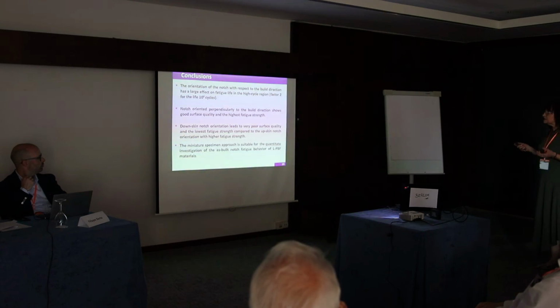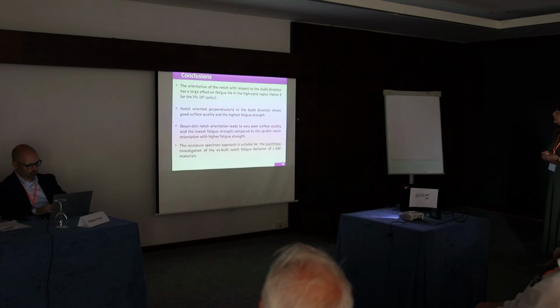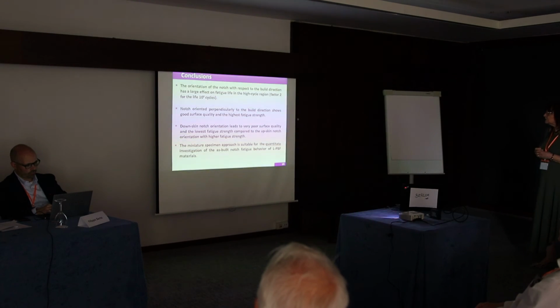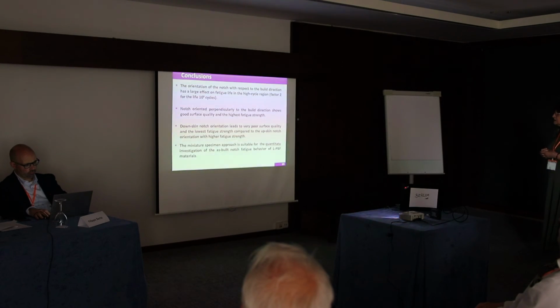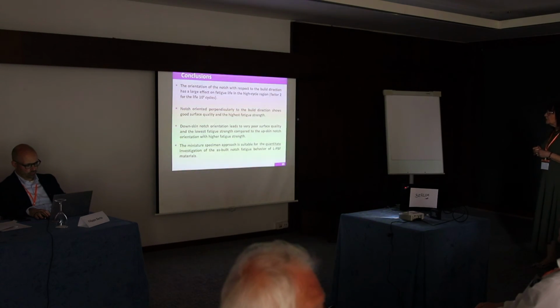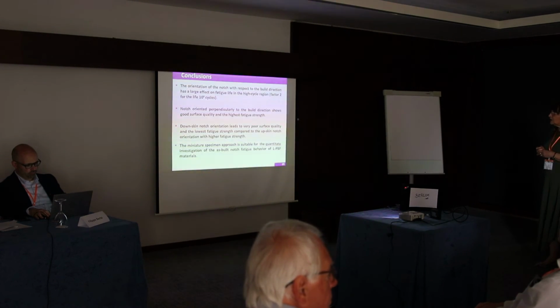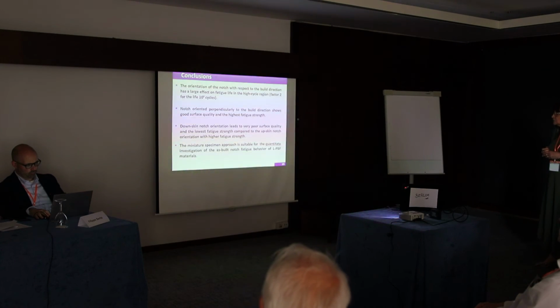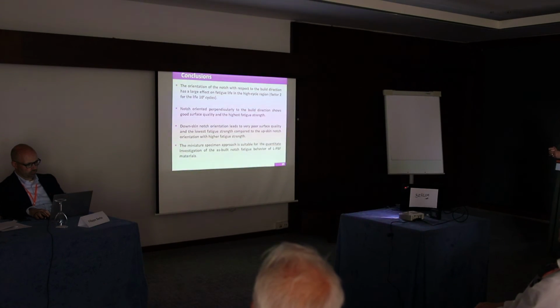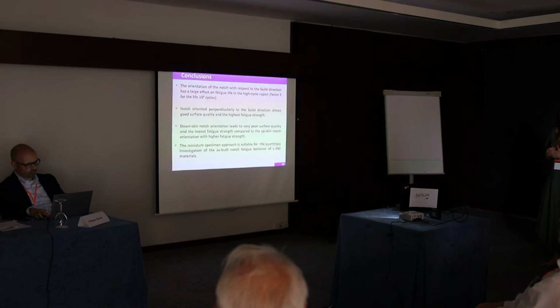And from this presentation we can conclude that the orientation of the notch with respect to the build direction has a large effect on fatigue life in the high cycle region. Factor 2 for the life at 10 to the 6 cycles. Notch orientated perpendicularly to the build direction shows good surface quality and the highest fatigue strength. Down skin notch orientation leads to very poor surface quality and the lowest fatigue strength compared to the upskin notch orientation with higher fatigue strength.